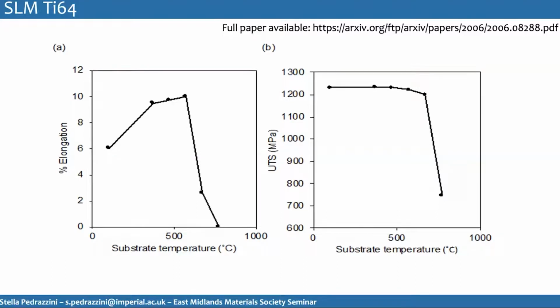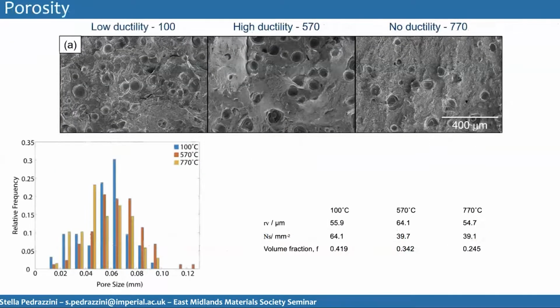We wanted to do this because if you heat treat them afterwards, you have a two-step process: you 3D print the sample and then heat treat it later. But if you can skip the middle step, we figured it would be quicker. But actually, it produced some very interesting results. The porosity was more or less the same. We quantified the porosity, and all three samples, 100, 570, and 770, the three more interesting samples, with some ductility, a lot more, and then 0 ductility, were quite similar in porosity, both in pore size and distribution.